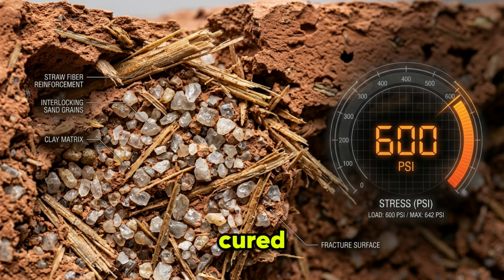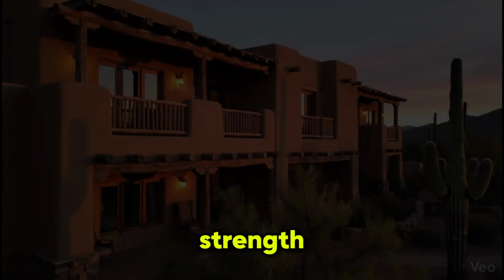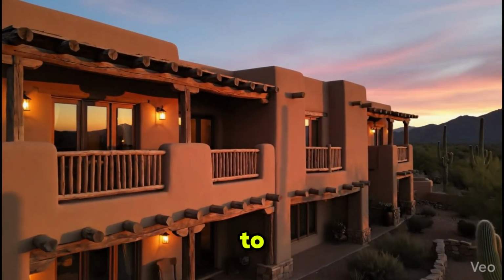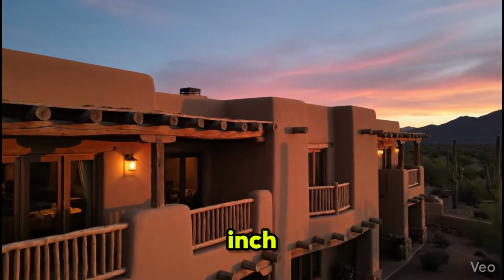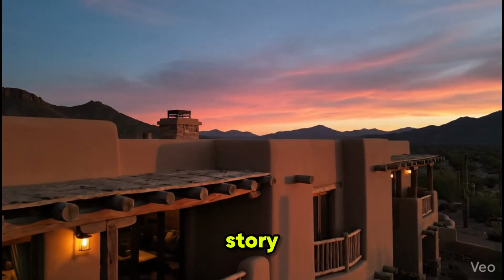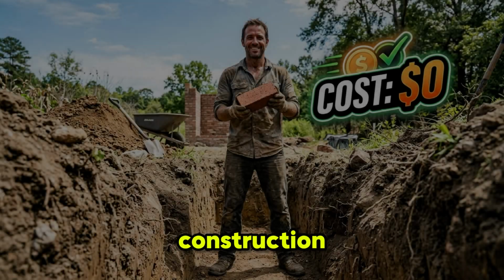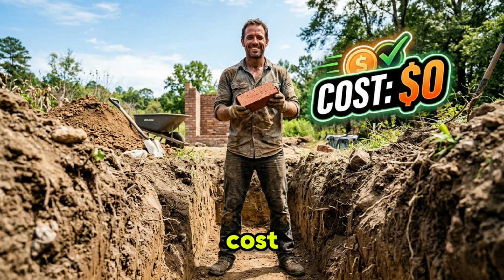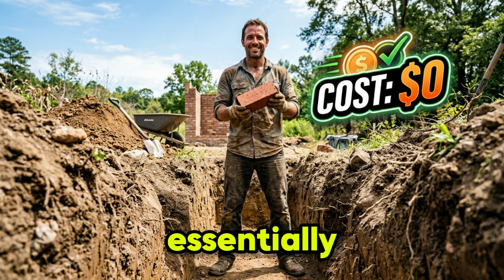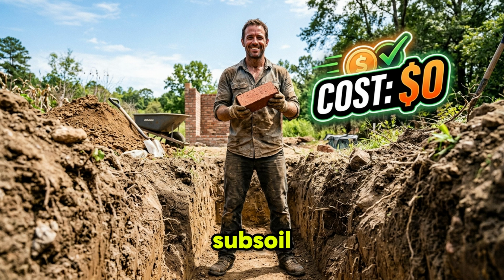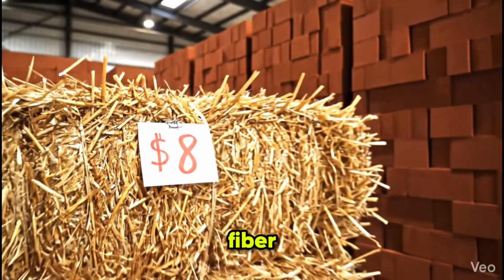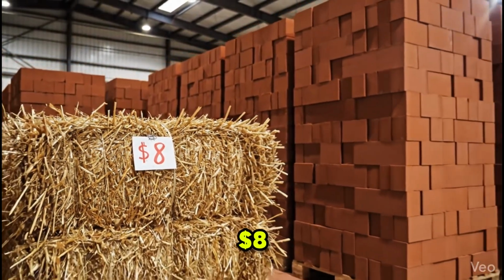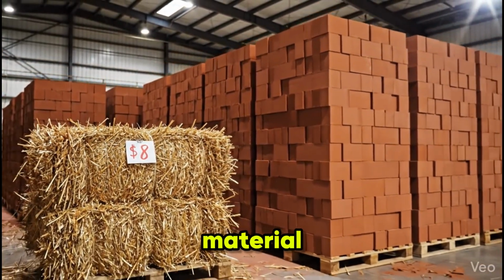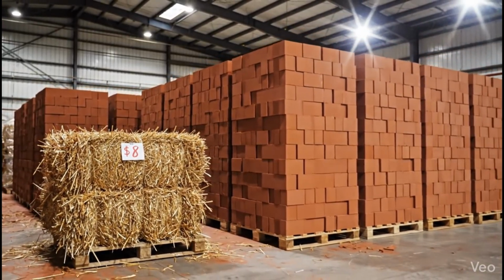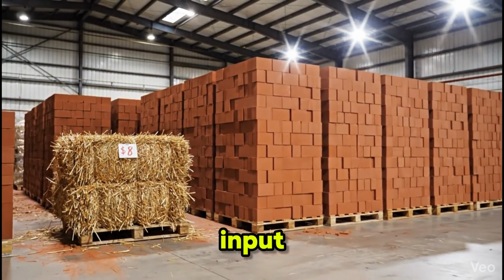A properly cured adobe brick has a compressive strength of approximately 300 to 600 pounds per square inch, which is adequate for single-story and many two-story construction applications. The cost per brick in materials is essentially zero if your subsoil has adequate clay content. A bale of straw for fiber costs approximately $8 and provides enough material for several hundred bricks. Water is the only other input.